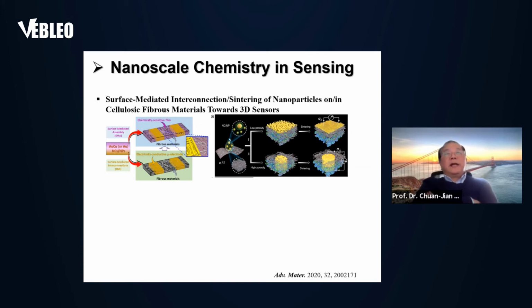Basically, we use nanoparticles to construct fibrous sensors. We load the nanoparticles, as illustrated on the left-hand side, and you can make electrodes by sintering. You sinter the metal nanoparticles, then you form electrodes inside the fibrous structure. Subsequently, you can load chemically sensitive nanoparticles on top, surrounding all the fibers. Then you can develop a sensor.